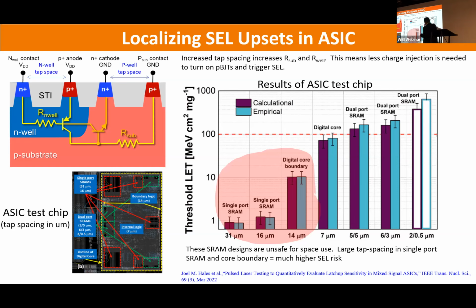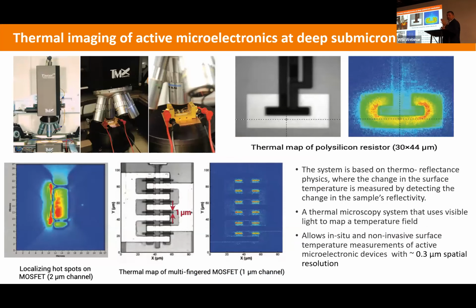And without going into a lot of technical details here, this is sort of the threshold at which a single event will happen. You can tell that by looking at this separation, which is the top separation. We can tell immediately that the wider this separation, the more likely that a single event will happen. So this is the type of data we can extract from this TPA, which will translate exactly what you would get if you were to measure this in the synchrotron. Except that in the synchrotron, you will evaluate the entire device. In this case, we can be very specific in terms of where this should go. Okay. Next one. So this is the last one before my conclusion.